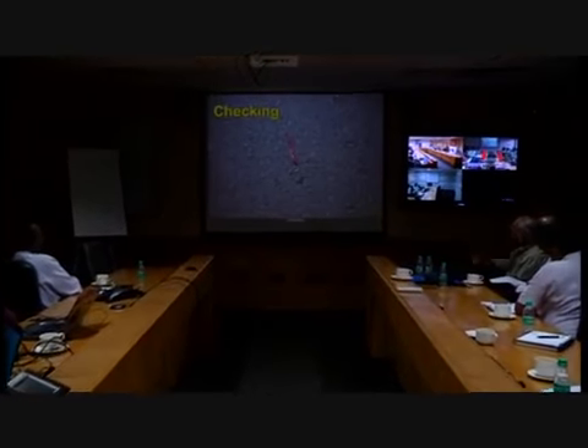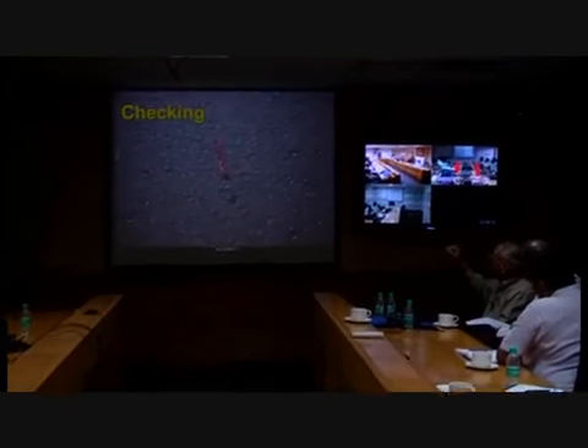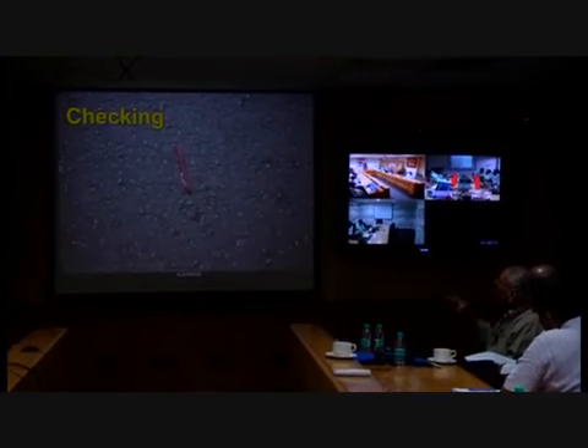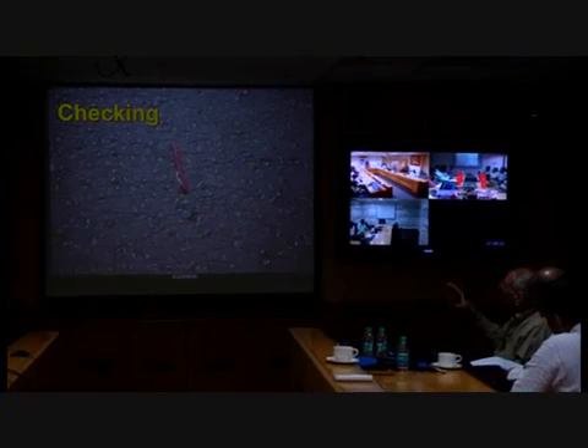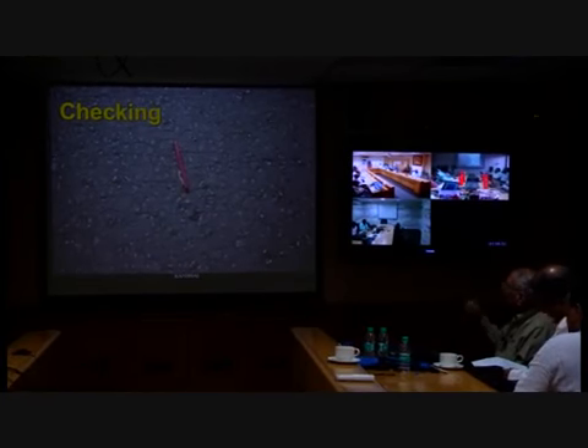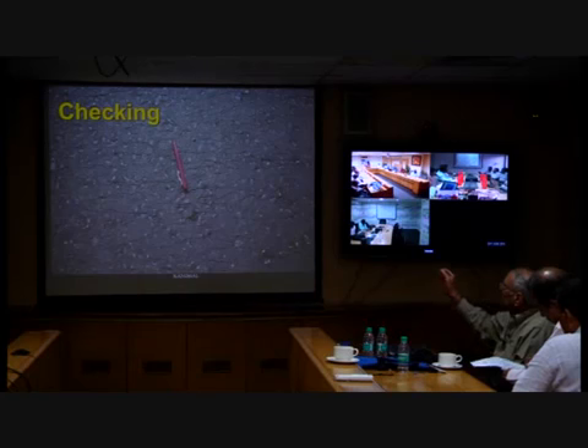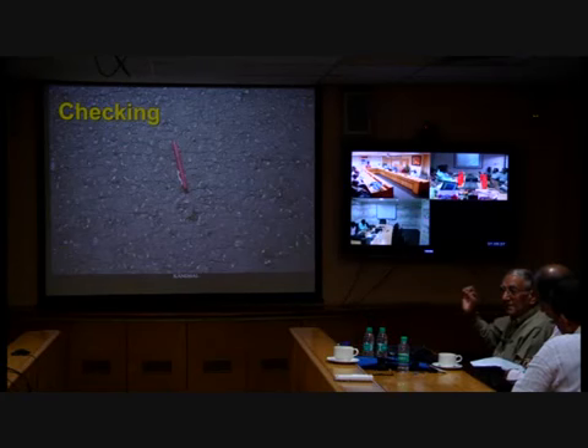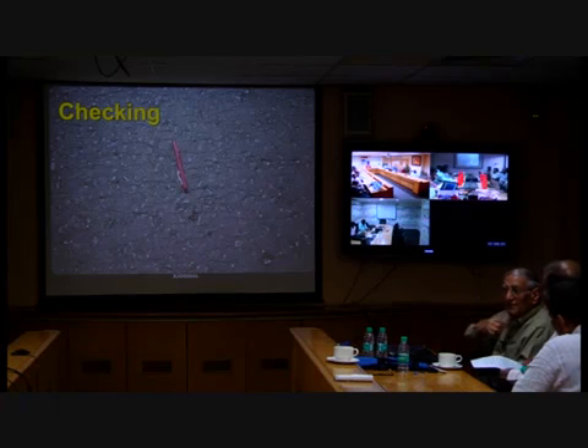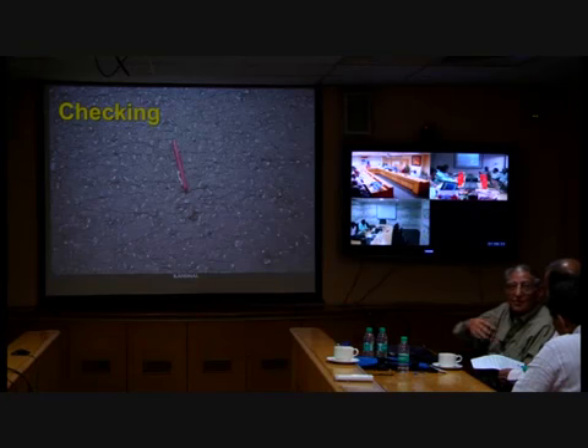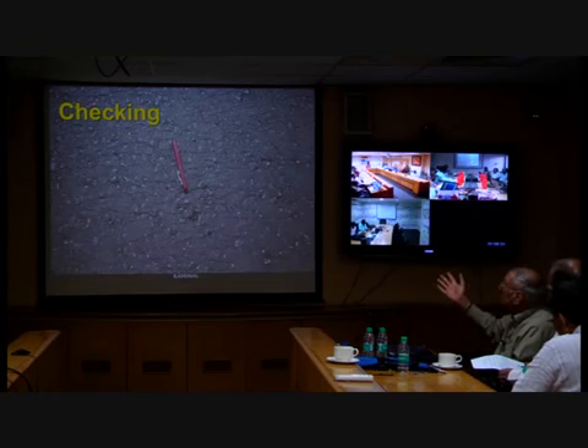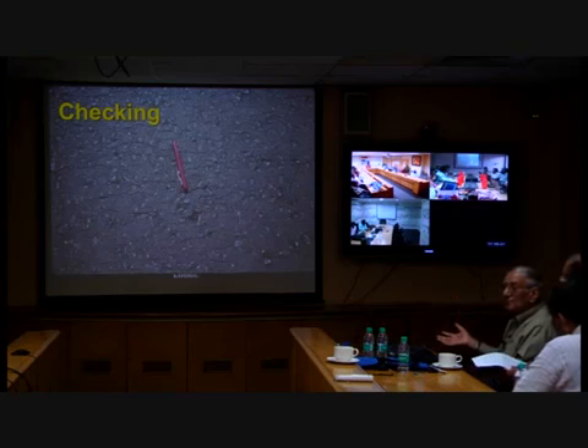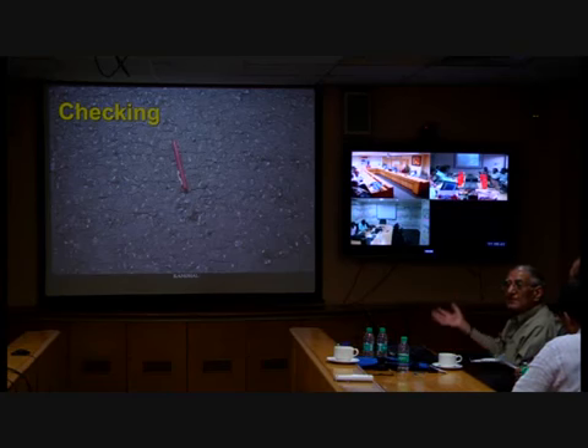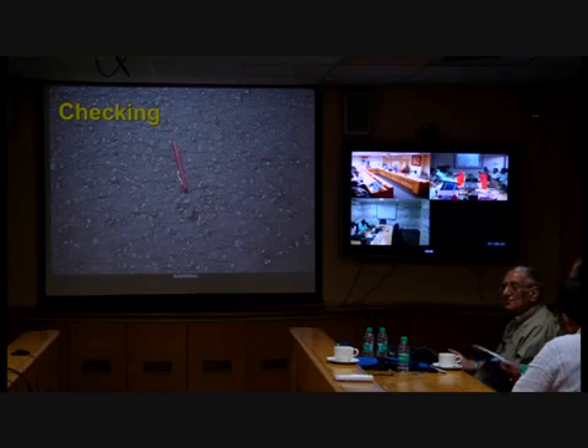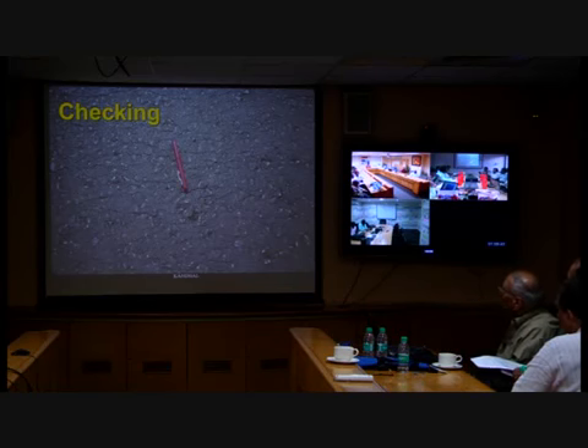Now this checking I throw in there, because you see the hairline cracking. Sometimes you will see it right away when the compaction is being done. After all the compaction is done, you see the hairline cracking, and with time, it can become somewhat widening. Prof. V. Raghavan and I saw this on DBM in Tamil Nadu a few years ago. And they had done a lot of work on the DBM already. If I see this kind of checking after I'm done with the compaction, I should do something right away at that point in time. Why should I continue my job? They didn't stop. So this kind of checking will occur